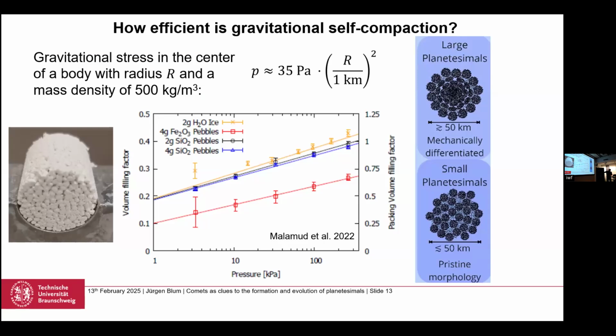And so we formed pebble piles in the lab. So every single white thing you're seeing here is a millimeter-sized pebble or so, again, consisting of micrometer-sized dust particles, again, silica. And we simulated what happens in a planetesimal. So this is the lithostatic stress in the center of a pebble pile of radius r in kilometers. And for a 1 kilometer radius object, this is 35 pascals, which if you have a feeling for pascals is not a lot. But if we're at 100 kilometers in radius, which is the typical size of a planetesimal, so we're here at 10,000, so we have 350,000 pascals, which is at the end here of the scale.